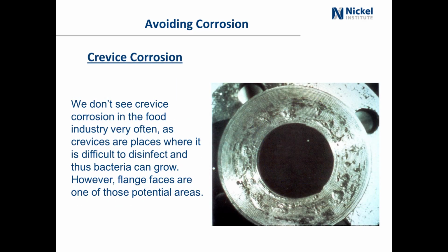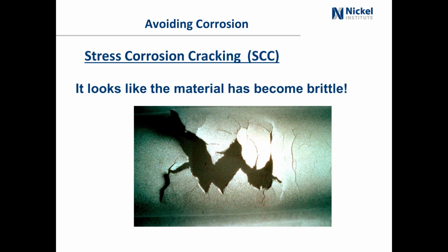Crevice corrosion. We don't often see crevice corrosion in the food industry because you're trying to eliminate any kind of crevices because the crevice is where it's going to harbor bacteria. However, flange faces could be one place where you might see crevice corrosion because you've got a crevice between the gasket and the flange face. Then there's stress corrosion cracking, which is another localized corrosion. And in this case, it looks like the material has become brittle because you get very specific localized cracking due to the presence of chloride and temperatures.